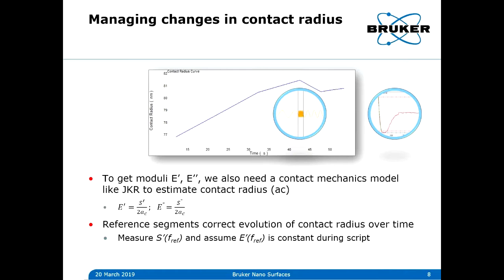That isn't necessary in the DMA case because the calculation is a lot simpler and a lot more things aren't resonating. And Bede, I would also just add from a very practical point of view, the frequency space for the fast force volume contact resonance versus this AFM-nDMA is very different. Relating to one of the earlier questions, not only is contact resonance very high frequency because it is based on where the fundamental eigenmode peak position is, but it's also at a discrete frequency that you have very little control over.